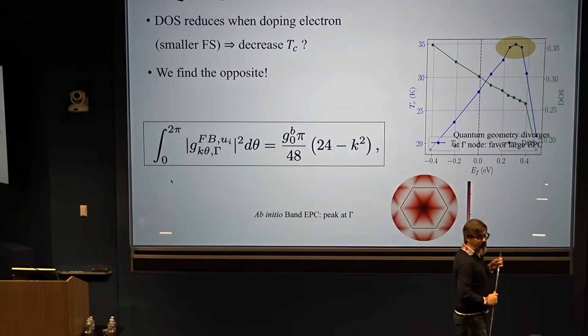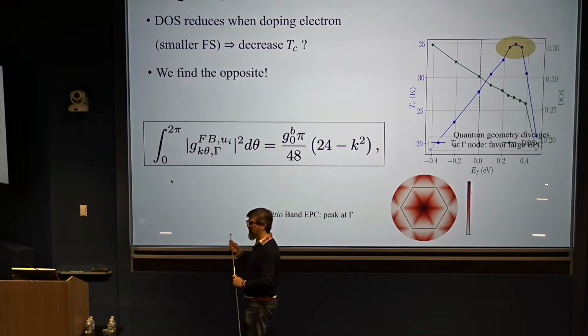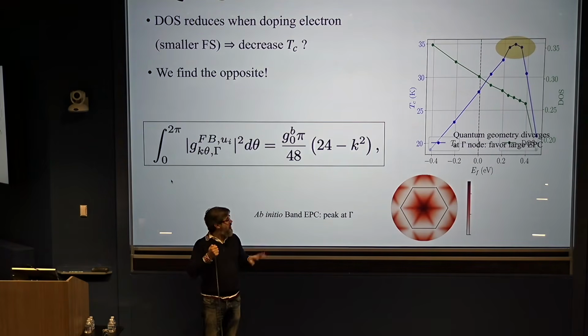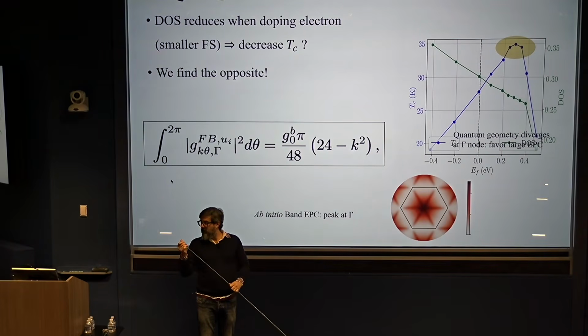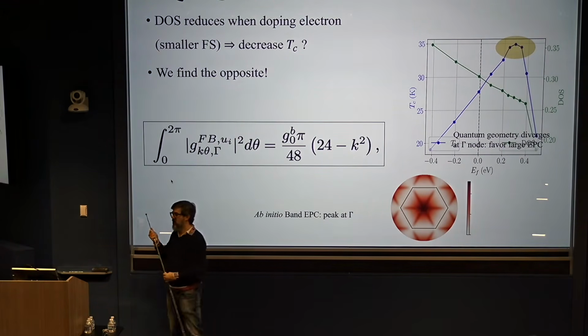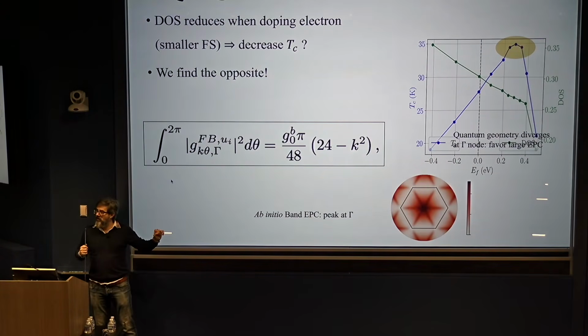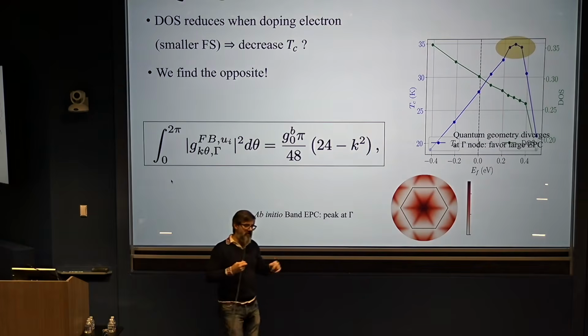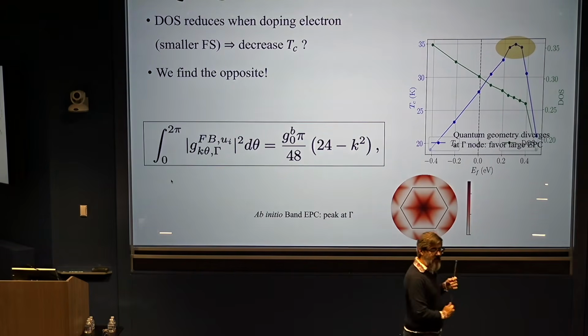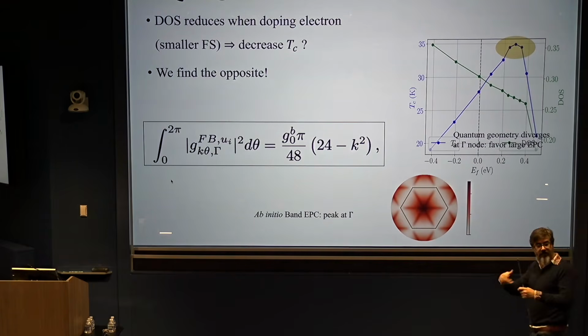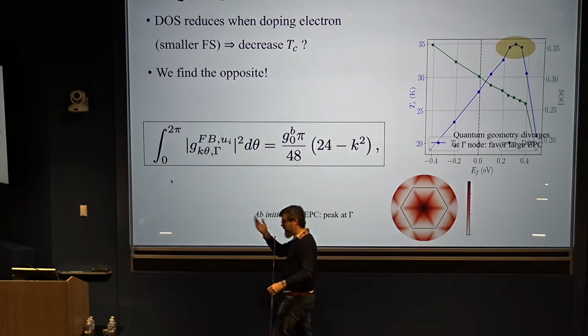So if you do DFT in Eliashberg, it always gets you lower TC in MgB2 than it is, as far as I remember. Paul is complaining that it's not the experimental TC, and I agree with you. This is just from the SP2. We're just plotting the SP2 Fermi surface here. These are theoretical, it's a theoretical TC. No, DFT, I understand, and it's only taking the SP2 Fermi surface. So there's another TC from the PZ. There's another extra 5 or 3 Kelvin or whatever.